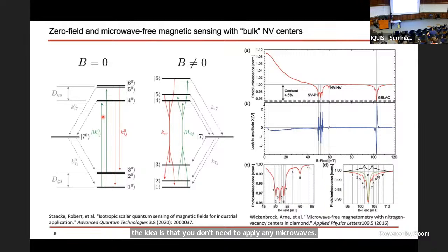under a non-zero magnetic field, the energy level system that I was showing in earlier slides consists of this ground and excited state triplet, right? And then this singlet state is the intermediate state. The green here represents the excitation, the red represents the decay. If you apply a magnetic field, you end up getting, as a function of magnetic field, changes in the rates of this decay, in both the pumping and decay rates. And at some point, you have basically crossing. This is known as a cross-relaxation phenomenon. What that means is that your photoluminescence, the level of fluorescence that you get at a particular pump power, is going to change depending on the amount of magnetic field applied.